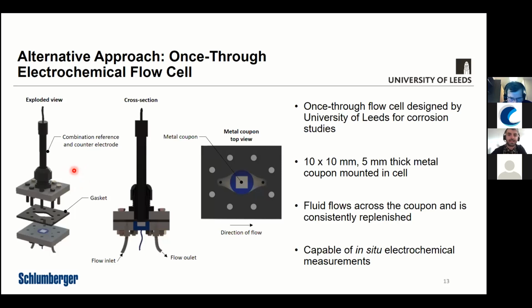For those that are completely unfamiliar with flow cells, they're essentially a small device that we use, which we would mount, in this case, a carbon steel coupon within the cell. We create some sort of flow channel across. This is a top view looking above the gasket layer. We create a flow channel for the corrosive fluid to flow across, in through the cell and out of the cell, essentially to provide an environment where we have really high precision, high control corrosion experiments.